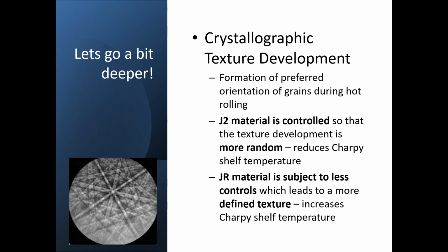But during the time of my PhD, electron backscatter diffraction as a method became widely used throughout the world to measure the crystallographic orientation of hot-rolled products, because it was found that in some hot-rolled products, there would be a preferred crystallographic orientation of the grains, and in others, it could be completely random. And what's important to point out is that because J2 is control rolled, the texture that develops is much more random, which reduces the Charpy shelf temperature. So it's actually this orientation of the grains and how the atoms orientate themselves during hot rolling that contributes towards the Charpy V-notch energy. The JR material has less control, which gives it a preferred orientation, which is not what you want in terms of mechanical properties.